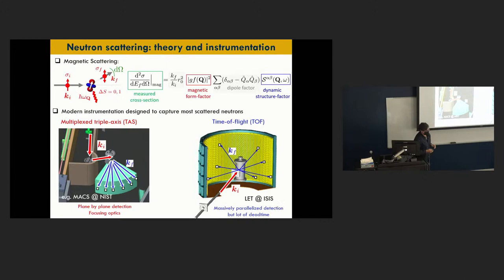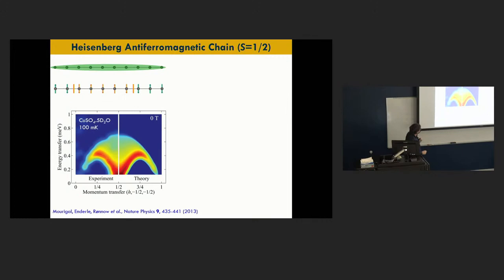Okay. So first, finally, some data that I took during my PhD on a very simple system. So this is copper sulfate. Copper sulfate is, in some approximation, at very low temperature, 100 millikelvin, a spin chain. And what we do here is we measure the excitations of that spin chain. Remember that I told you they should be fractional. I measure them as a function of momentum transfer, so the scattering angle along the chains, and energy, and you see the energy is very small, below 1 meV.